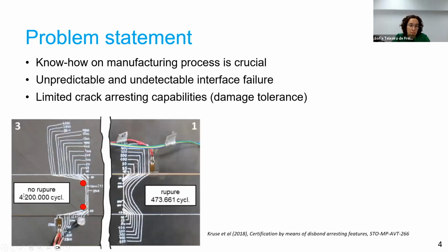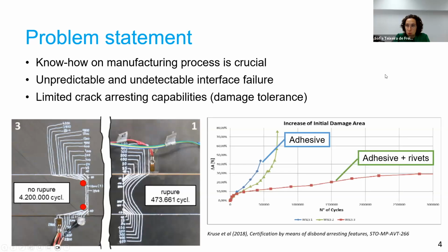So here are two specimens of a bonded joint. This area here is the bonded area, the overlap area. And these are fatigue tests. This one has 2 rivets drilled in the composite, in the bond line, and this one doesn't have any rivets. This is a test performed by Airbus in a European project called BOPAX, and these are the results.